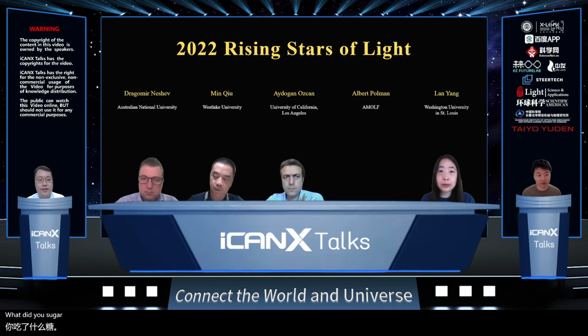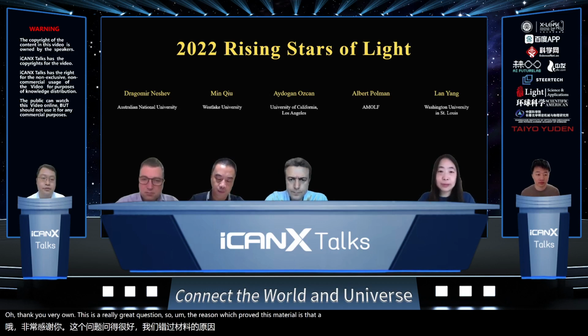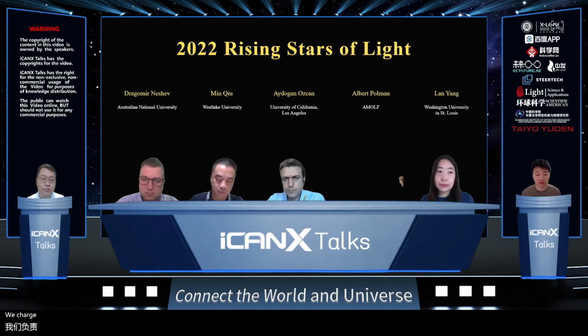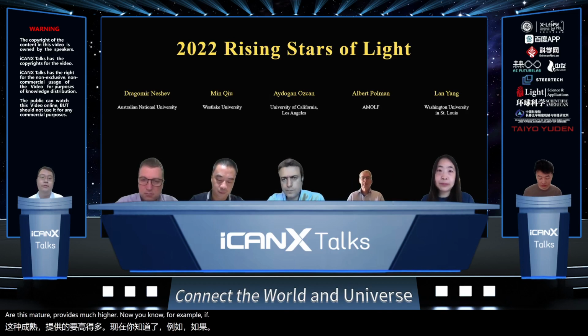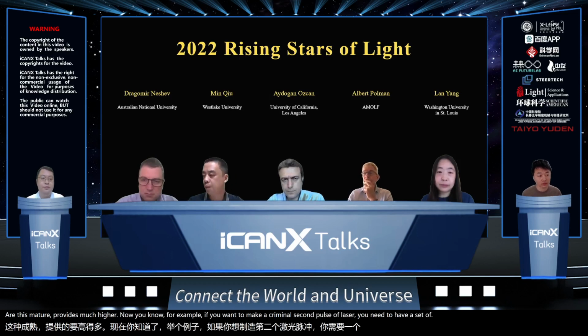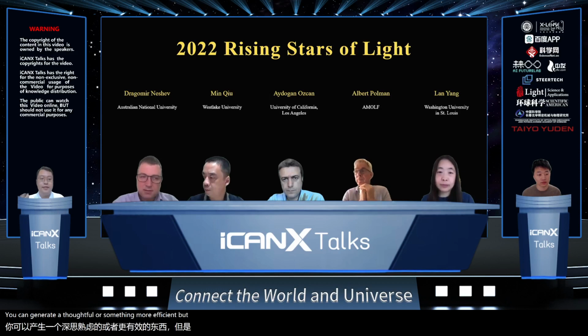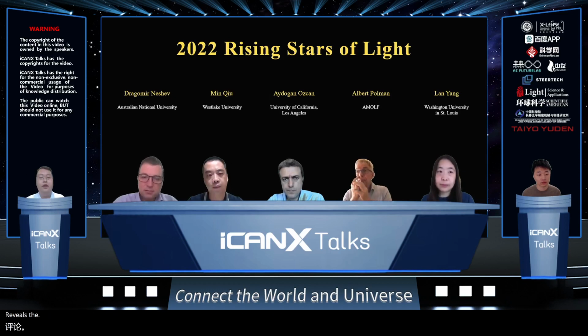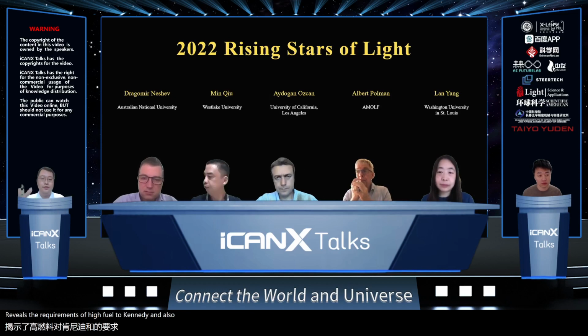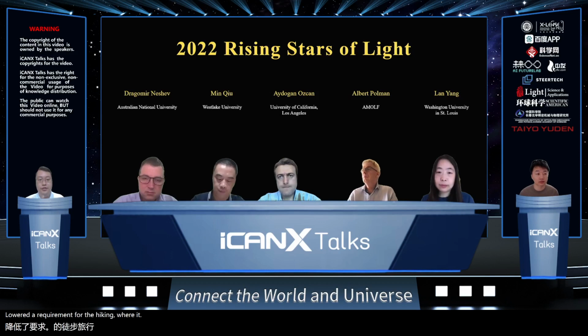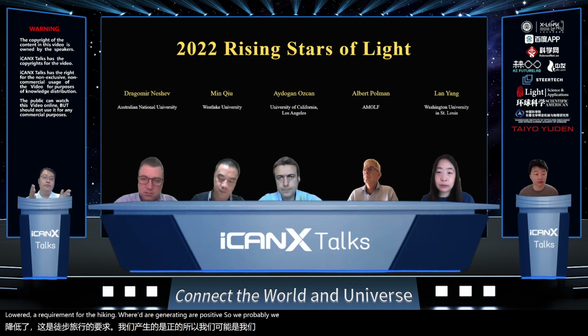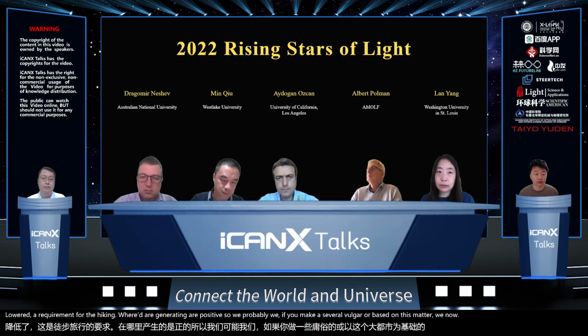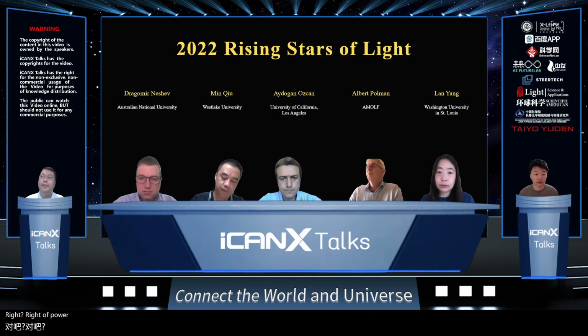Okay. Thank you, Professor Yang. This is a really great question. The reason we choose this material is that compared to silicon or silicon nitride, which are cheap and more well established, this material provides much higher nonlinearity. For example, if you want to make a femtosecond pulse laser, you need some saturable absorption or nonlinear effects so that you can generate a soliton more efficiently. But with this Chi2, we can reduce the requirement of a high Q optical cavity, and also lower the requirement for high gain for generating pulses. So if you make a saturable absorber based on this material, we require a much lower threshold power. Okay, this is one thing.